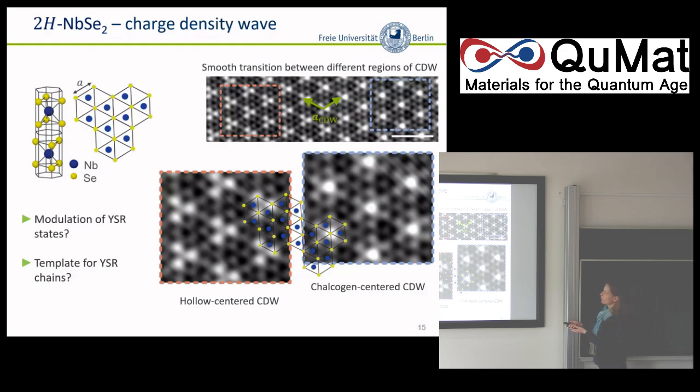Okay, that's fine. First of all, you notice that there are lattice sites where you basically have a niobium below, or you don't have a niobium below. These are 2 distinct adsorption sites. But for instance, here you can have an adsorption site which is just on top of the maximum of the charge density wave, while here it would be impossible. Instead, you're very close to it.